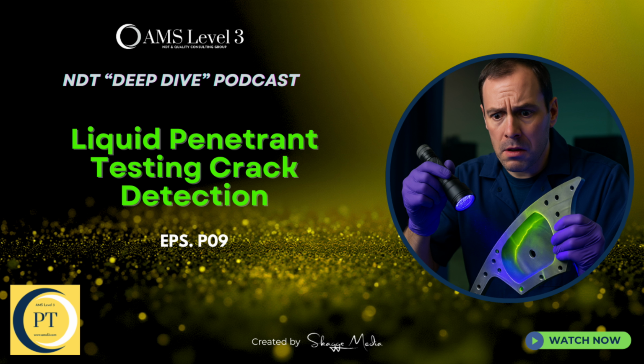So if capillary action is the engine, you mentioned dwell time earlier, this time the penetrant sits on the surface. Is that like the throttle? How much does that vary? It varies a lot, and yeah, that's our first major control point. The dwell time needed depends completely on the material being tested and the kind of flaw you're looking for. You see, penetrant gets into wide openings pretty fast, but for those really narrow, tight flaws, like fatigue cracks maybe, you might need 2 to 5 times longer for the penetrant to fully soak in compared to a wider flaw. Wow, that's a big difference.